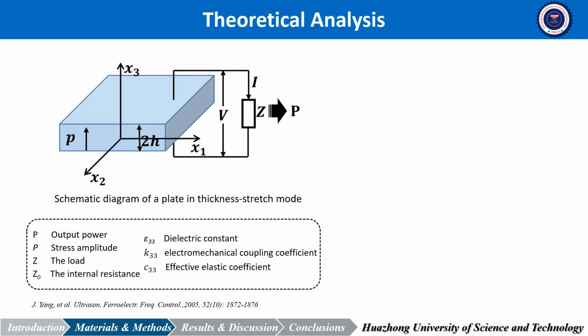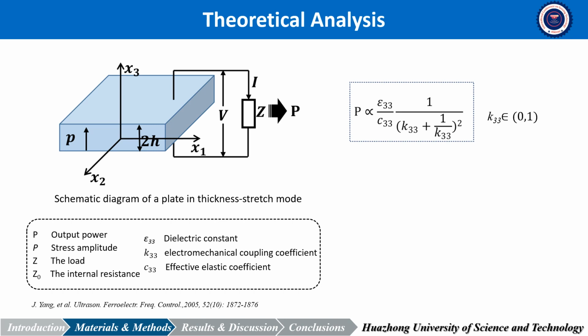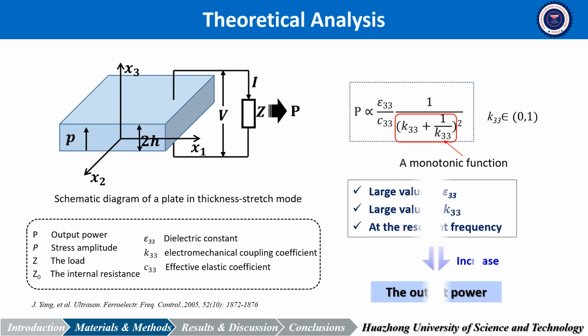According to the piezoelectric ultrasound energy harvesting theory, for a plate in thickness stretch mode, the output power of the device can be expressed as a formula given here. K33 is the electromechanical coupling coefficient, which changes from 0 to 1. So, this part is a monotonic function. Therefore, for the purpose of increasing the output power of the device, the first thing you should do is to select the piezoelectric materials with large dielectric constant and large electromechanical coupling coefficient. And then you should make this material work at the resonant frequency.